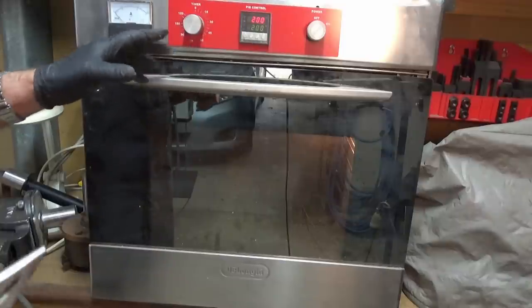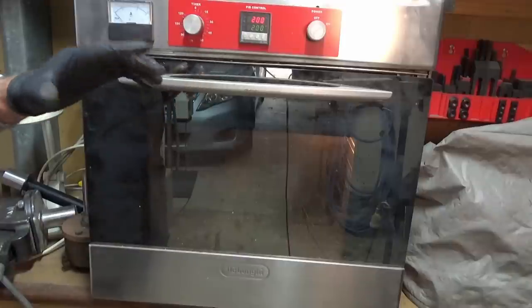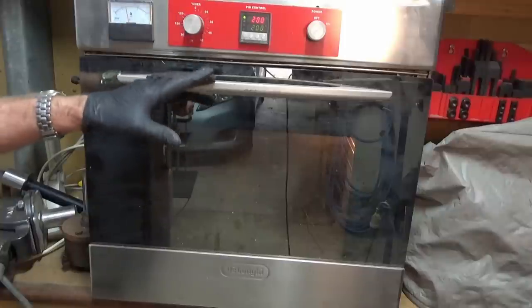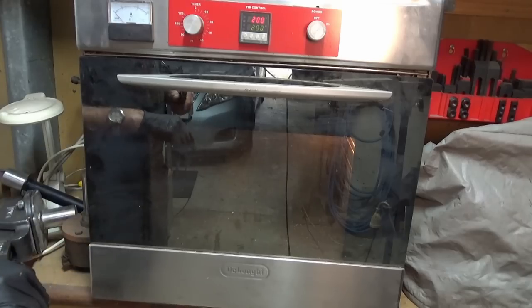Now, depending on the size and the weight of the part, it can take between 5 and 20 minutes for the surface to start to change. When you see the surface texture start to go smooth or glossy, you then leave it for another 10 to 12 minutes for the powder to fully cure. When that happens, just take it out, hang it up, let it cool down in air.